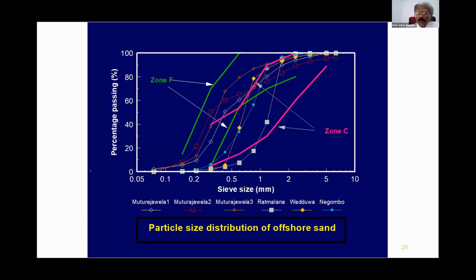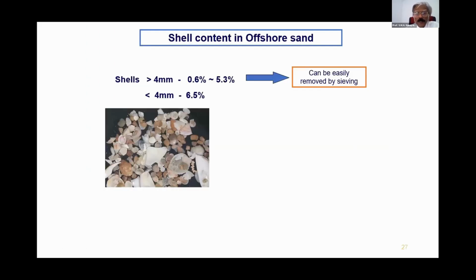And this shows the particle size distribution of offshore sand taken from several locations. Now, depending on the location, you can see that it varies from fine zone to coarse zone. Now, this is not a big issue. The particle size distribution is not a big issue. Depending on the particle size distribution, we can adjust the mix proportions and come up with the required performance of the concrete. The next is the shell content in offshore sand.